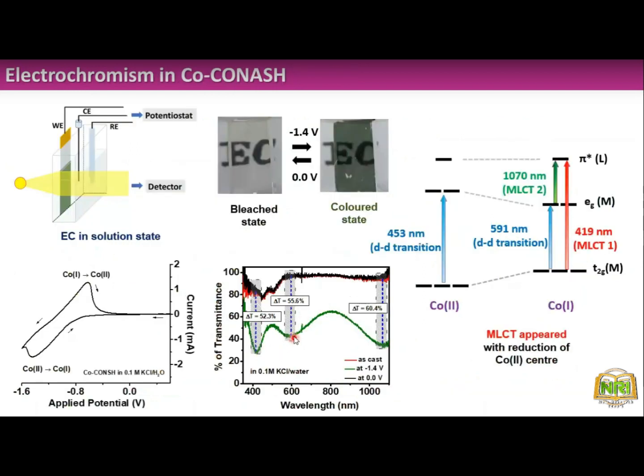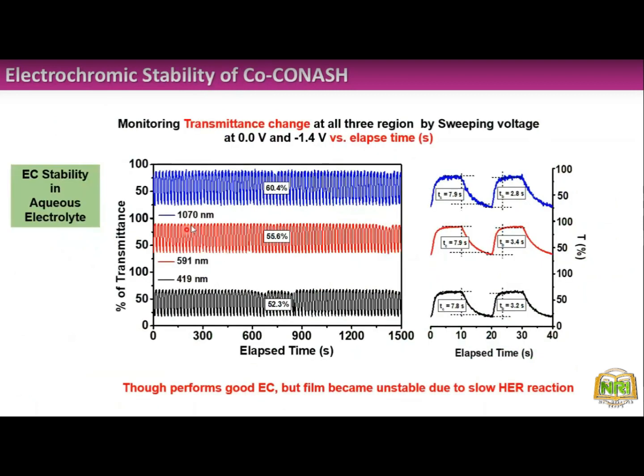So we have to check the electrochromic stability at these 3 wavelengths, and we have seen that up to 1500 seconds, that was very stable. But after that, the film was degrading.